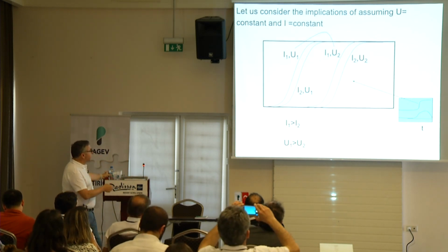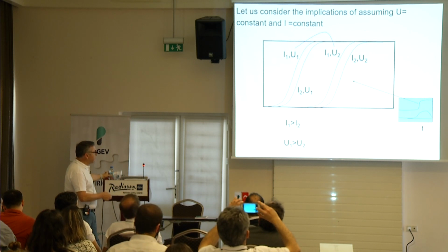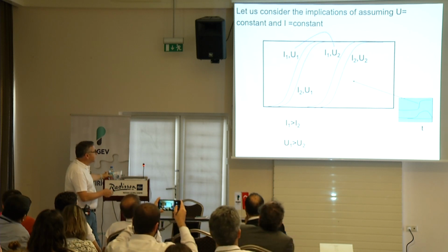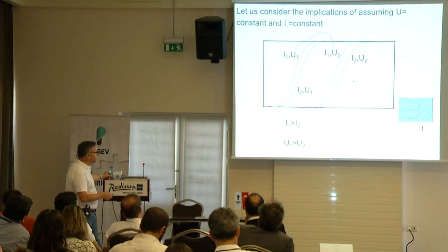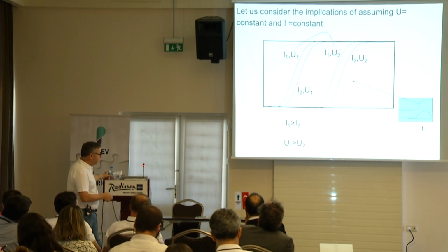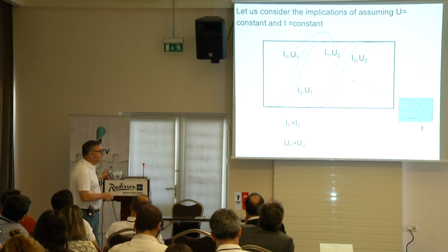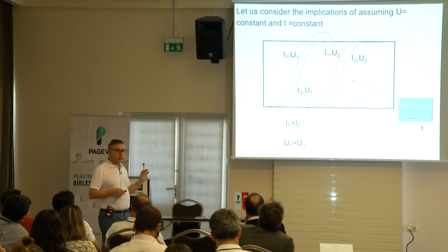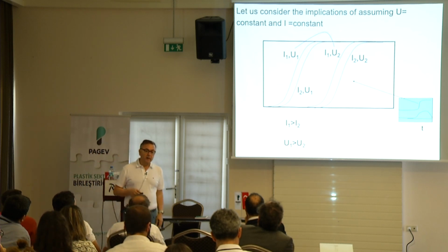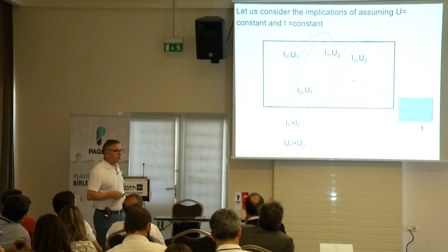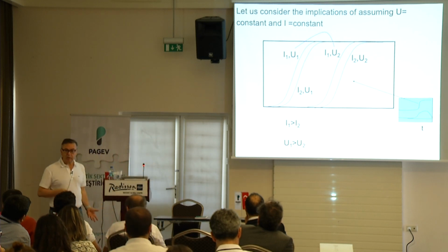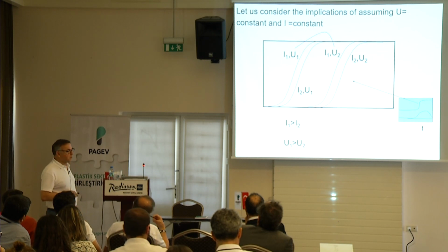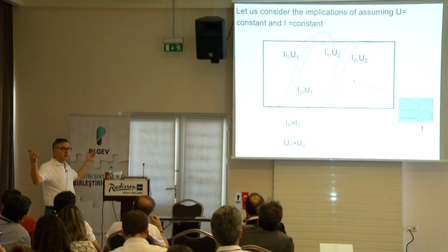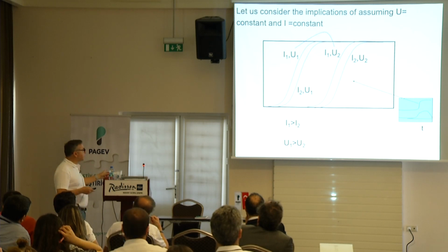What's powerful, and this is demonstrated here, is that if you change a little bit of growth rate, the crystallization rate dramatically changes compared to the nucleation rate. Even though we know this, we still try to play with the nucleation rate by putting in nucleating agents. Growth rate is not so easily controllable because you don't want to sacrifice the molecular weight. So you just try to nucleate as many crystals as possible so that they all start at the same time, and then you convert them into a final solid product.